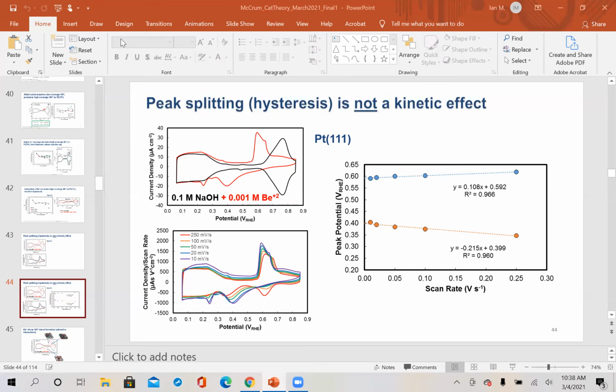Sure. So that is a very interesting question. And I'll say maybe if we want to be super rigorous, there could be lots of things going on here. I think here we went with the simplest explanation that can explain this hysteresis. But yes, if you scan to high potentials on platinum normally, without beryllium, you'll see what we expect to be an oxygen adsorption peak, and there's a peak splitting, typically because we assume oxygen adsorption kinetics are slow. But we do know this place exchange occurs.